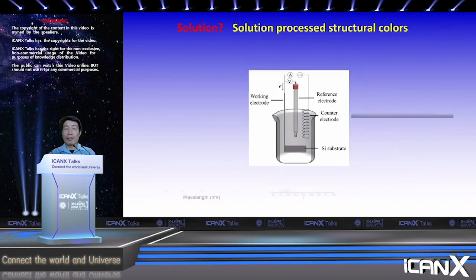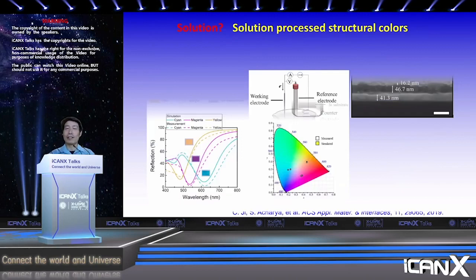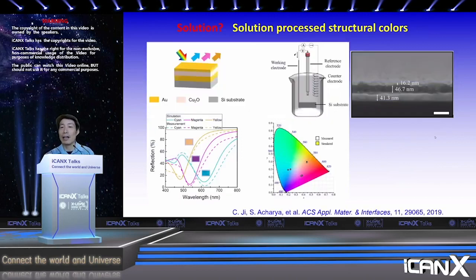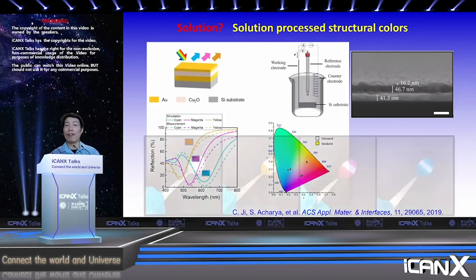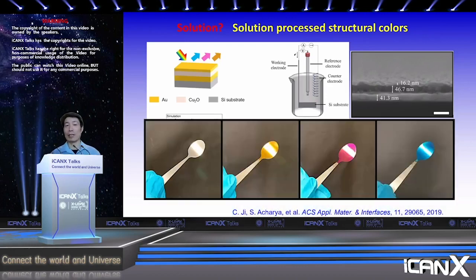So in fact, after many trials, we were able to achieve this. On the upper right, you can see these layered structures by electrodeposition, down to tens of nanometers thick, reasonably smooth, which can give rise to optical quality. Again, using this simple three-layer structure, you can create the cyan, magenta, yellow color. Now, this could lead to a potentially much cheaper process. But another great advantage, I think, is that now it doesn't have to be flat, right? You can have a curved object, like shown in here. You take a stainless steel spoon, and you can actually coat different colors on it. You can take an arbitrary 3D object, basically.